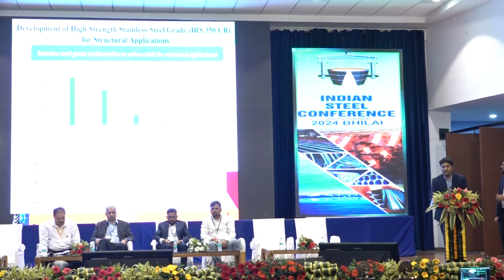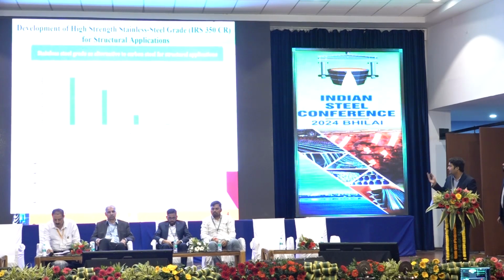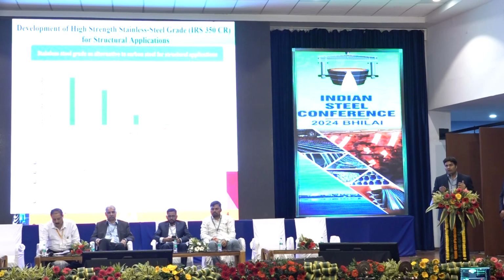In this table, we can clearly see the corrosion test we have done, the salt spray test, in which we can see the carbon steel has 19.55 milligram per area corrosion, compared to the SS, which is the IRS 350, which has 0.107 milligram per area. So we can clearly see that there is 200 times less corrosion in stainless steel compared to the carbon steel that is presently applicable in most of the structural bridges or foot over bridges.